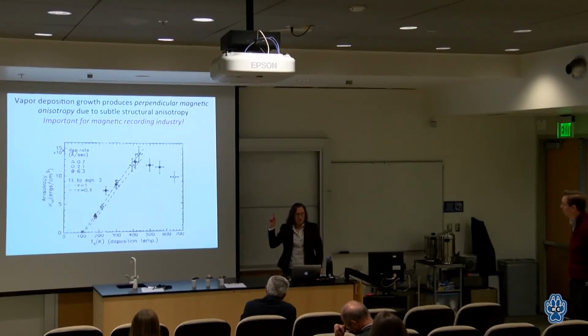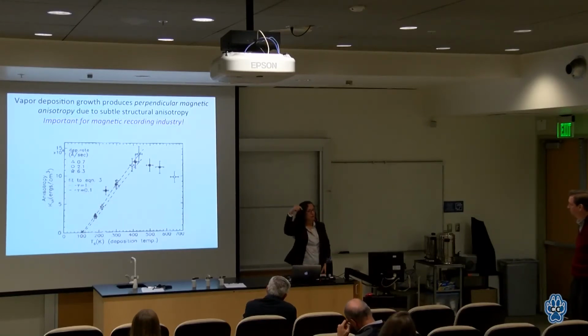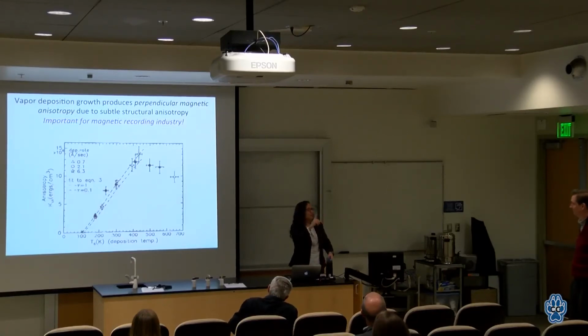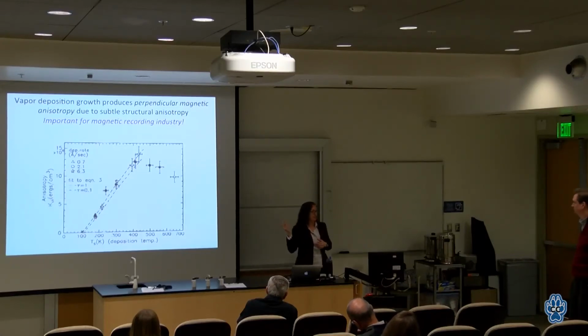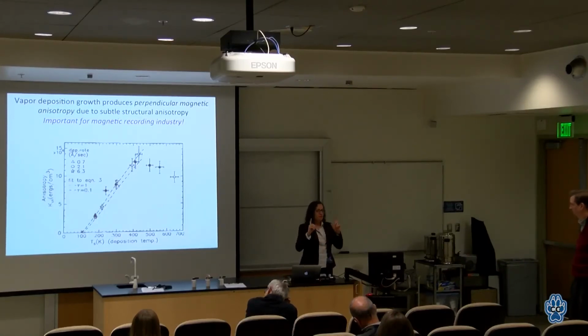First thing, the first place this was actually used was in a technology that was called mini disc technology, which actually required a magneto-optic recording system. So it bounced light. And so it had to be out of plane because the polar Kerr effect is the one you need. So there was sort of a practical nature of that. They were actually fairly large bits at that point, but they were using light. It was the very first read-write disc technology that existed, the magneto-optic effect. So there it was out of plane.